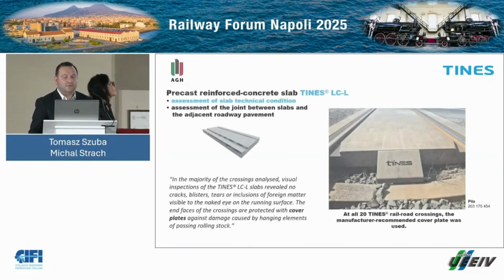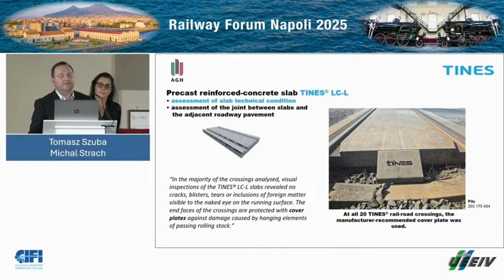Across most sites, slabs showed no cracks, blisters, tears, or foreign inclusions on the running surface, and faces are protected with cover plates. Local issues were linked mainly to the slab asphalt joint and edge loading. The fix is straightforward: restore joint sealing, repair adjacent asphalt, and keep drainage effective.